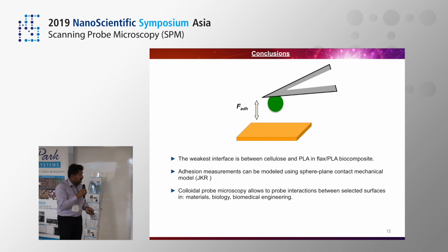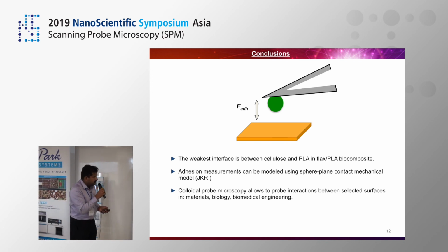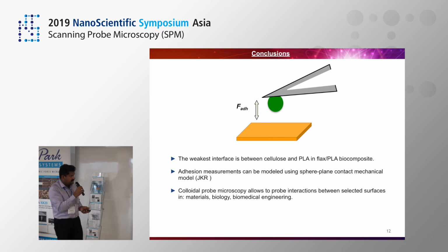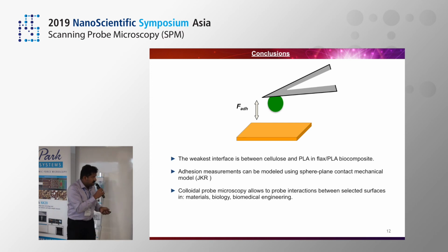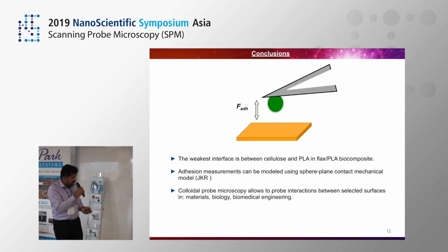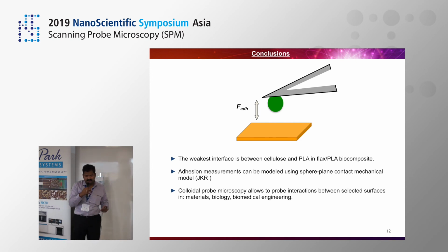So as a conclusion, colloidal probe AFM shows that the weakest interface in a biocomposite is between PLA and cellulose. The adhesion force measured can be modeled using sphere plane contact, and this is not limited to this system but applies to any other systems which have been discussed on this floor before, for example, to study the interactions for bio recognition. Yeah, that's what is written.